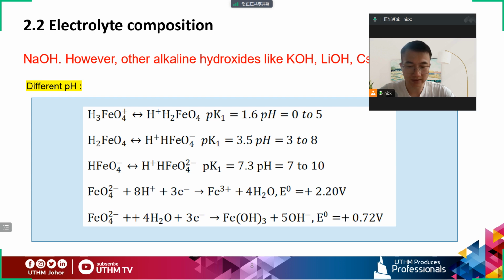It has been observed that the degradation of ferrate occurs at a first-order rate. To synthesize the ferrate, the electrolyte is typically maintained under strongly alkaline conditions. A mixed electrolyte exhibits advantages in the synthesis reaction. However, excessively high sodium hydroxide concentration may result in electrode passivation, and the percent of ferrate adherent to the anode could impact the ongoing oxidation of the iron atom.